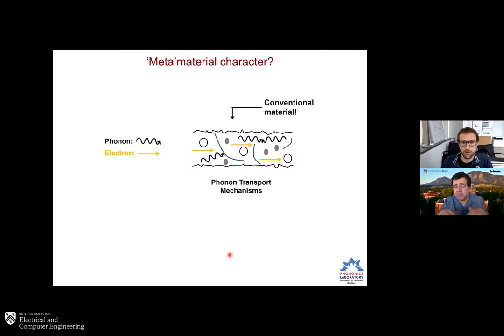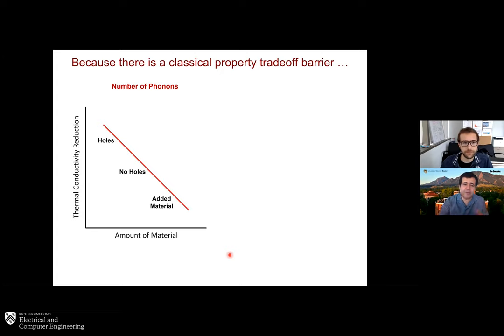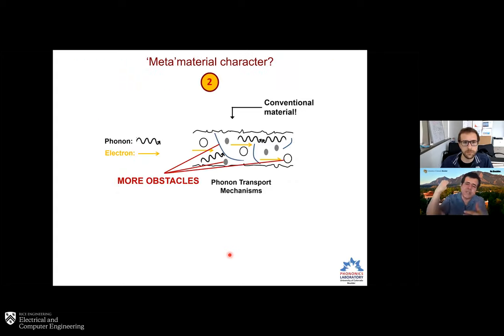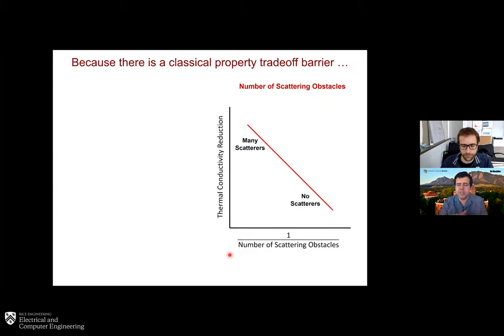And even more can be said about the use of the term meta. So I have further cartoons here to show you. Imagine this picture that I showed you before. Now I'm showing some rough surfaces. So you have less material by adding some holes. It's well known that if you have more holes, you will reduce the thermal conductivity more, and vice versa. So typically you live in this trade-off. And then similarly, if you add scatterers to impede the phonons, you can also draw a similar picture and recognize that you increase the thermal conductivity reduction by reducing the scatterer spacing. So you get this trade-off as well.